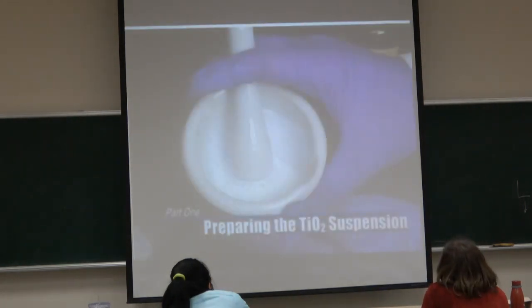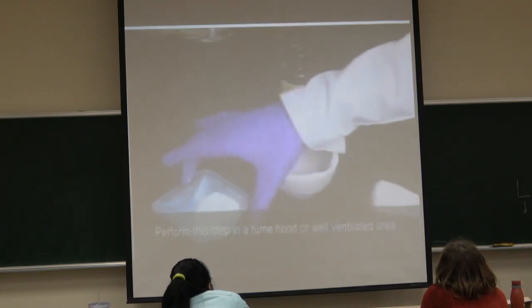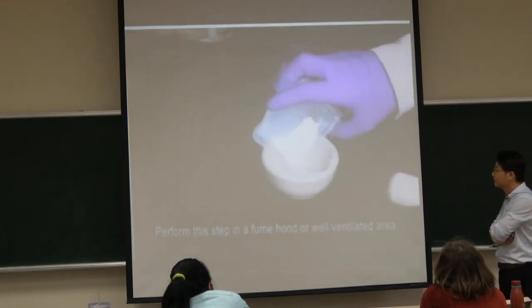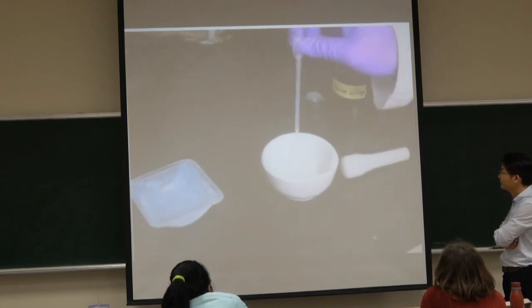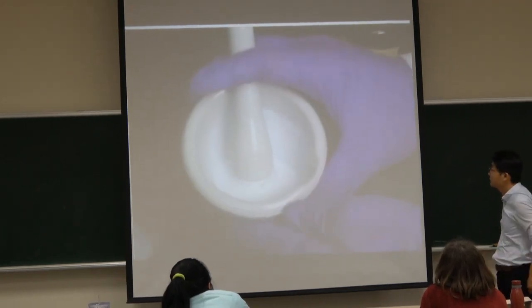Part 1. Preparing the titanium dioxide suspension. Step 1. Start with 6 grams of titanium dioxide powder in a mortar and pestle. Under a fume hood, slowly add vinegar in 1 milliliter increments to the solution. Grind well each time. The process will take around 30 minutes and will result in a very white, milky, paint-like